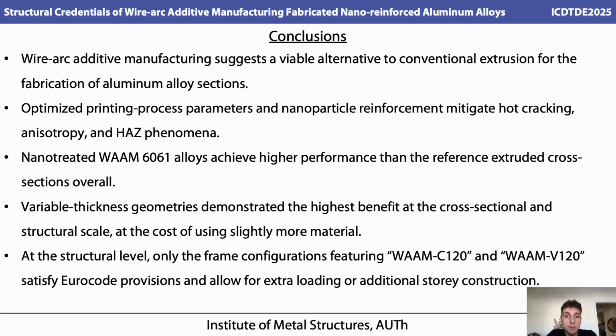Optimized printing process parameters and nanoparticle reinforcements mitigate hot cracking, anisotropy, and HAZ phenomena. Nano-treated WAAM 6061 alloy achieves higher performance than the reference extruded sections overall, as we saw in both the cross-sectional analysis and the structural analysis. Variable thickness geometries demonstrated the highest benefit at the cross-sectional and structural scale at the cost of using slightly more material, 7% and 40% more material, while our improvements were around 75% and 78%, if I remember correctly.